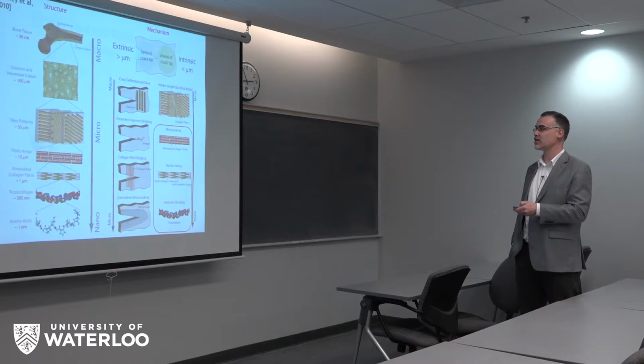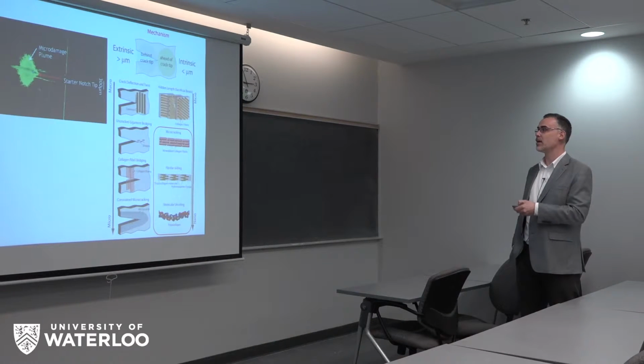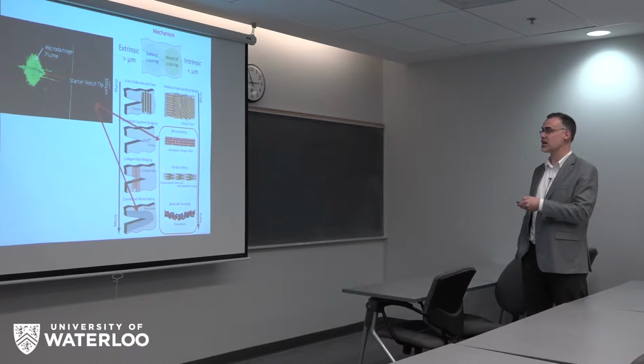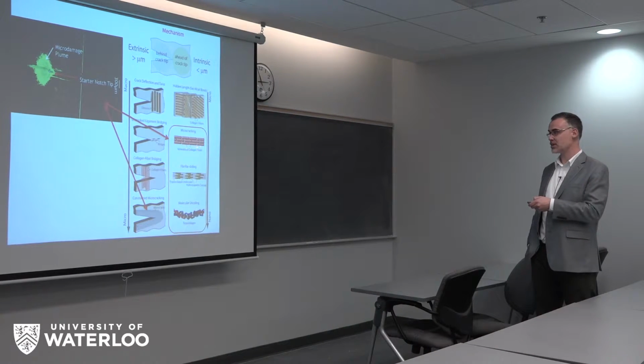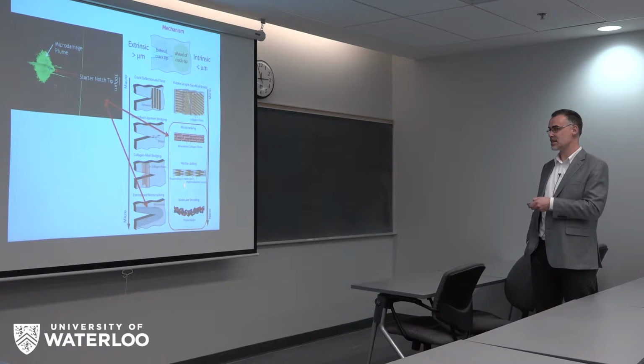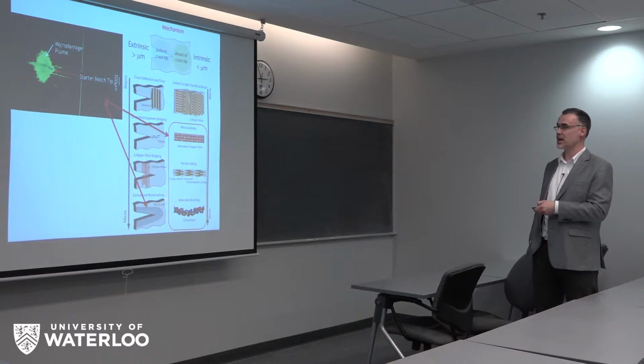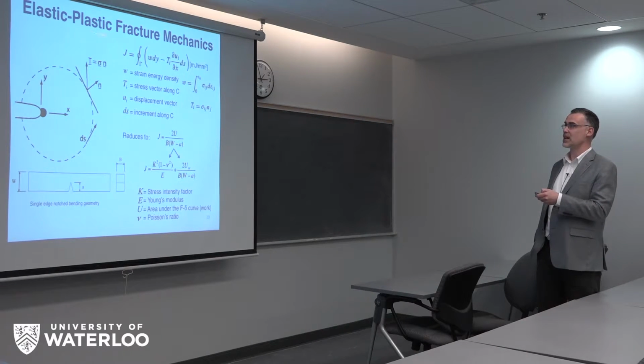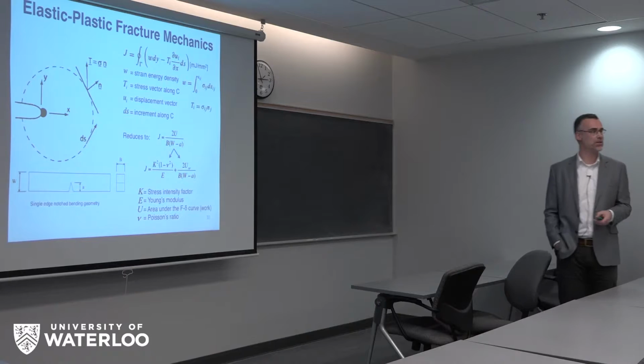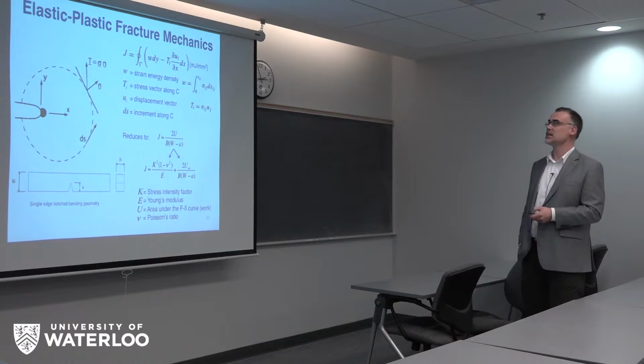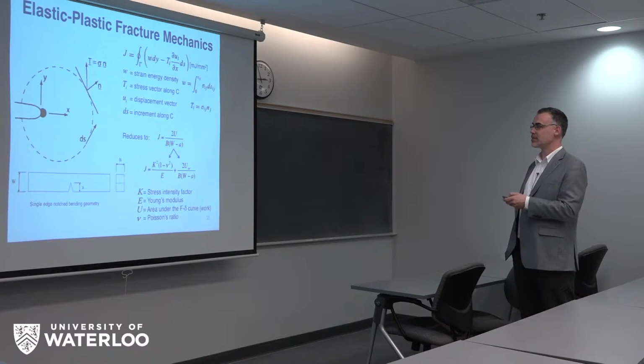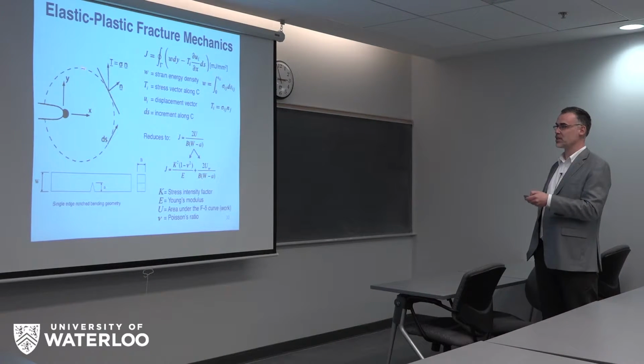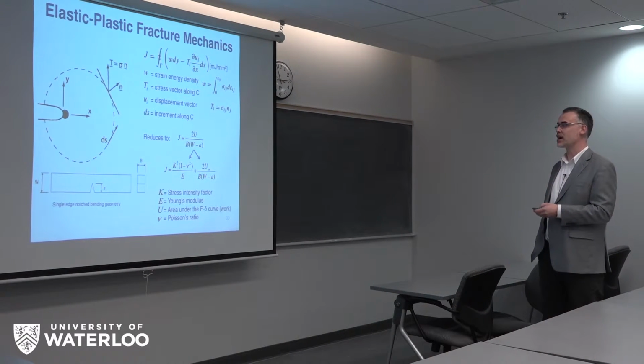And so for these reasons of the process zone forming, microcracking ahead of a crack tip, this is all happening at the very small scale, down to the sub-nano scale, microcracking of the mineralized collagen, plasticity in those fibrils, and microcracking, we end up using elastic plastic fracture mechanics to try and capture some of the irreversible effects. It's an integral. It's called the J integral. You integrate around the crack tip.